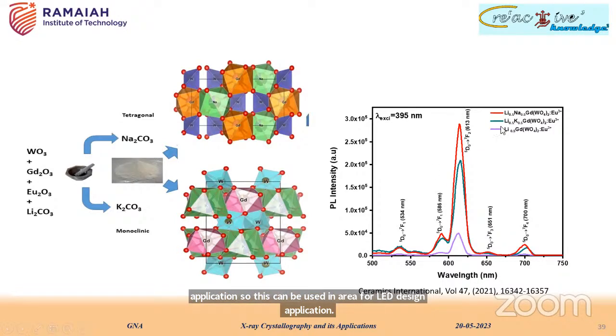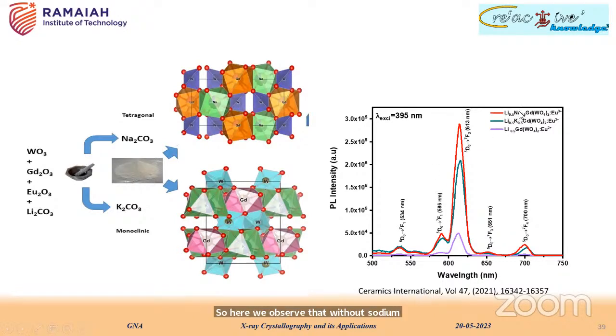Here we observed that without sodium and potassium, we got a very little intensity, this curve. And the sodium has actually enhanced this intensity. So sodium is an activator. Its presence has increased the emission intensity by many folds. This is because of the structure. You can see here the tetragonal is actually favoring more compared to the monoclinic phase.